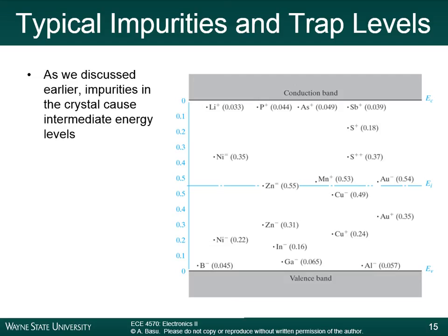If you have ions in there, if you were to use tap water, for example, which as you know has a lot of ions in it. Well, if you happen to have copper ions in your water, guess what happens to your silicon? Copper creates intermediate energy states within the silicon. If any of those copper ions get into the silicon wafer that you're washing, then you end up having intermediate energy states. Your material will not behave as a typical semiconductor material will. Copper, magnesium, even small amounts of gold, zinc, these types of ions are common in city water. But copper, I would say, is more common. You have copper pipes, and sometimes the copper ions from the pipes leach out into the water.